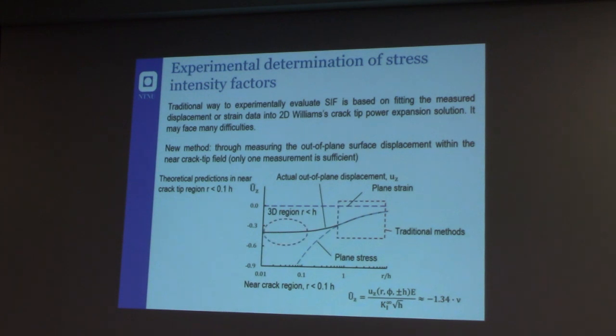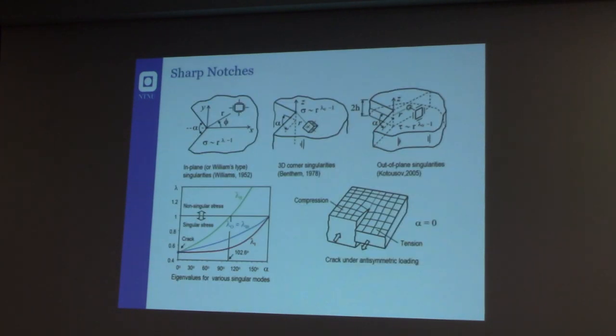And what we did also was to extend the consideration to notch components. So we simply went ahead with the same approach. We added the thickness to sharp notch components, and what we found was that Williams' solution also has some limitation because it doesn't consider, of course, the thickness effect.